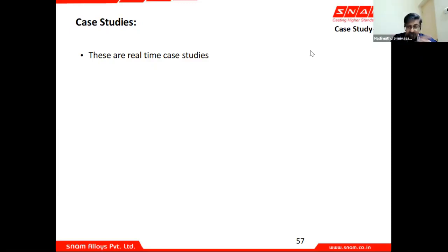And we did some experiments. We have done a charge mix, as Mr. Sandeep said. There are some other case studies being prepared at the R&D center. We have found that trying to avoid pig iron doesn't provide good nucleation sites. From our experience, we would definitely recommend a minimum 10% pig iron. I hope I have answered your question of what was used in the experiment.